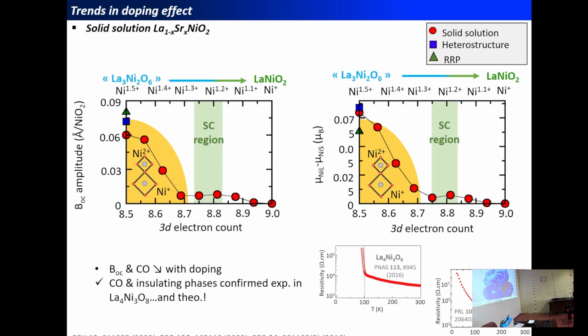And so the existence of charge ordering and insulating phases associated with these intermediate doping contents is effectively observed experimentally in the next member, which sits just right here, and it's observed with a metal-insulator transition around 100 Kelvin.